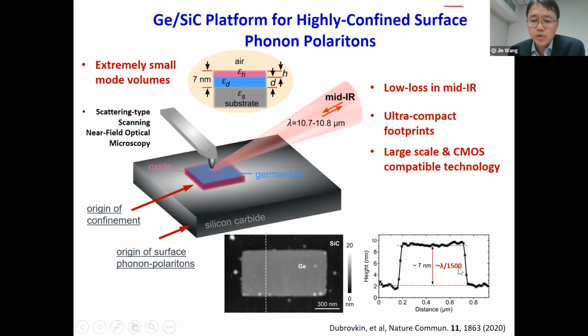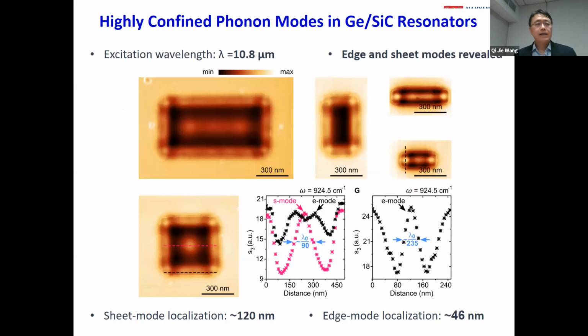And here we use E-beam lithography and thermal evaporation to fabricate relatively high quality germanium on silicon carbide substrate. And laterally, such a system can also support highly confined Phonon-Polaritons. So here we fabricate several resonator devices to show such capabilities, with device dimensions from a few 100 nanometers to a few micrometers, shown right here. And the interesting part is that we are not only observing the so-called sheet mode that has a resonance inside the cavity, but also along the edge. We call it edge mode.